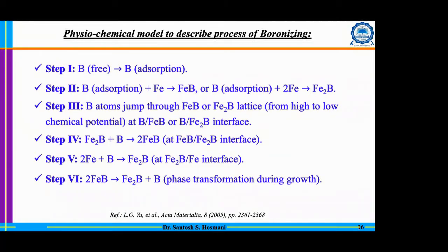You have the free boron, which is coming from the atmosphere, and this boron potential depends on a lot of factors. One is the chemistry or composition of your boron mixture, as well as the temperature. Then there is adsorption of boron, and that adsorbed boron will react and form the FeB and Fe2B. Now again, formation of FeB and Fe2B depends upon the capability of the atmosphere. If the boron potential is high, then only there will be the formation of FeB. Otherwise, it will not lead to the formation of FeB.